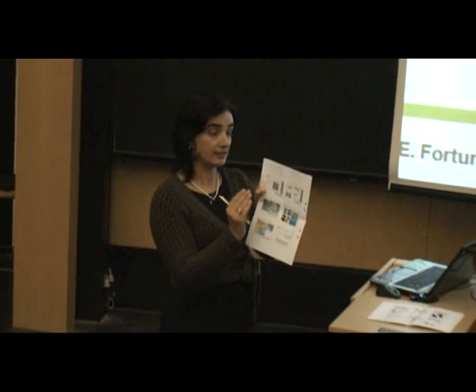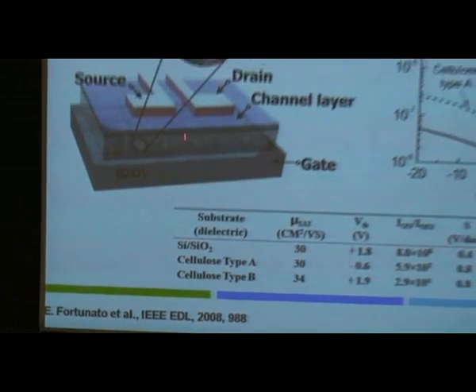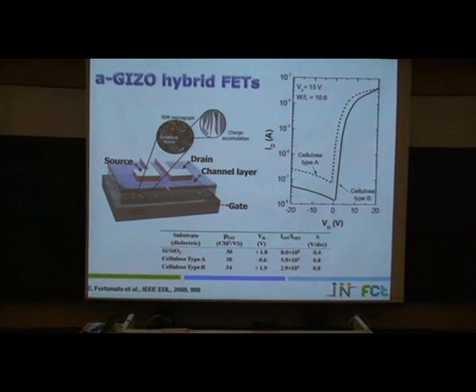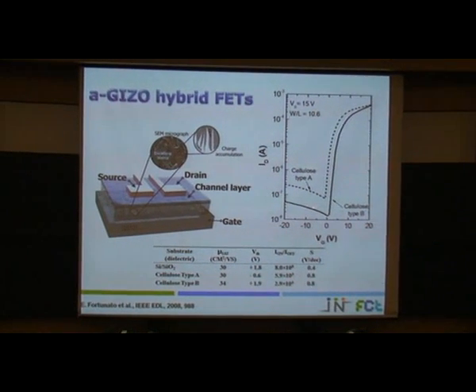from the dielectric layer. On one side we cover with the gate, on the other side we cover the sheet of paper with the semiconductor and the source and drain. This is the configuration of the device. We use for the gate electrode IZO, amorphous indium zinc oxide. This is the sheet of paper, the GIZO semiconductor, and the source and drain. And these are the results for two typical TFTs, or FETs, because this is a hybrid, it's not a TFT in the sense of the word. By using, for example, two types of paper, we can achieve nice curves.